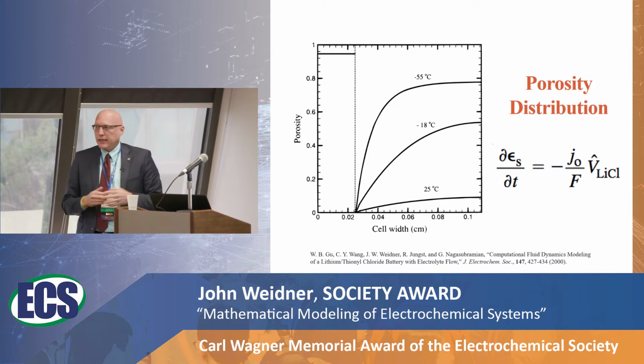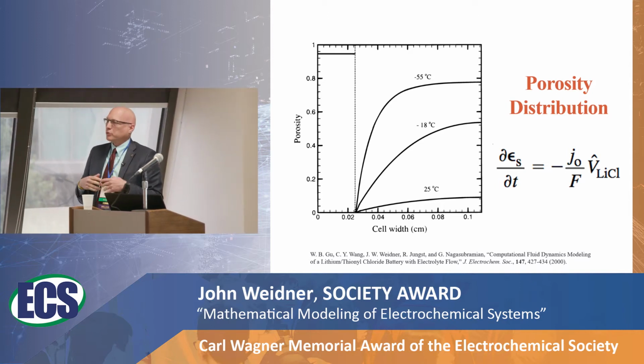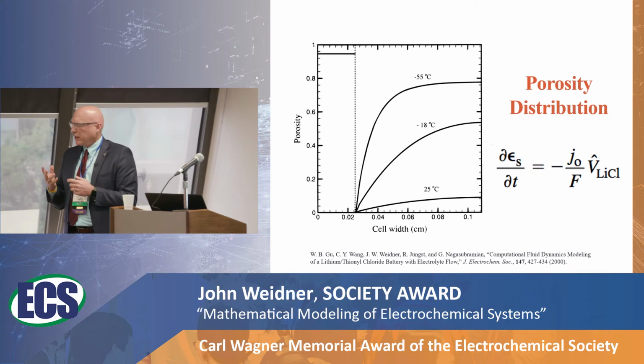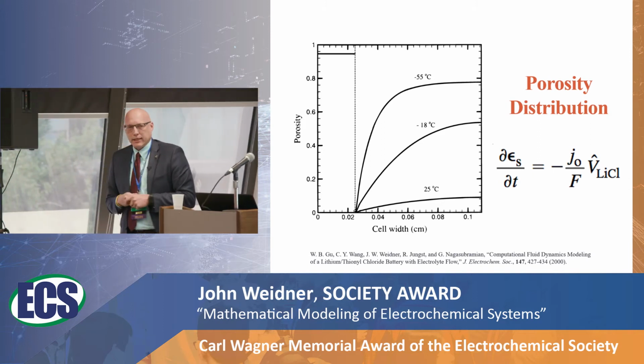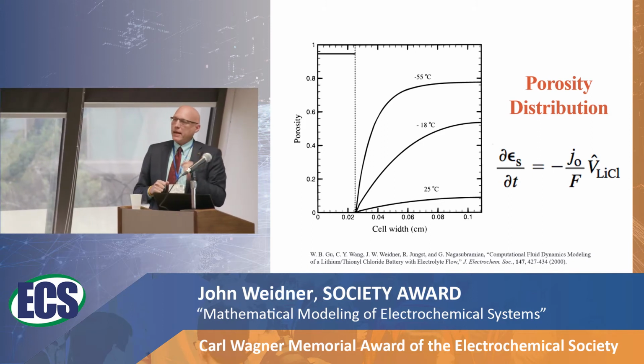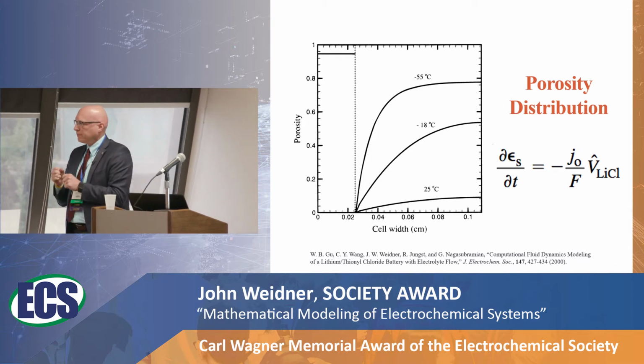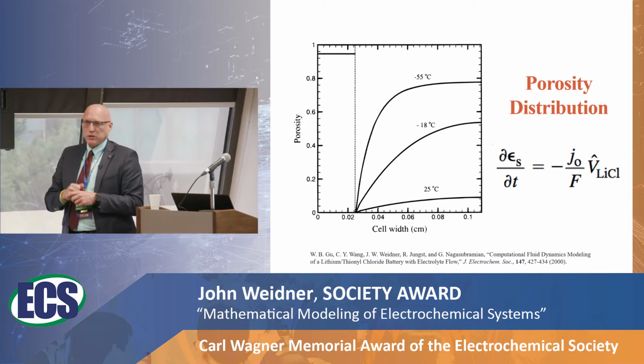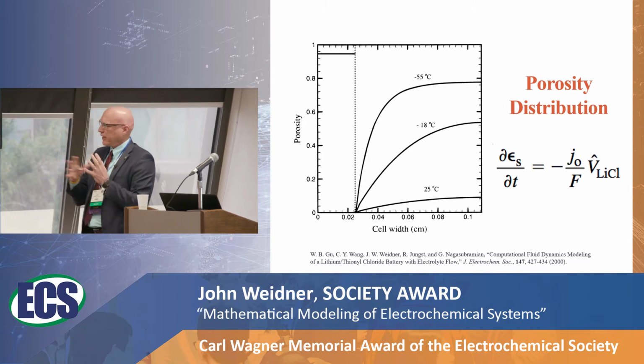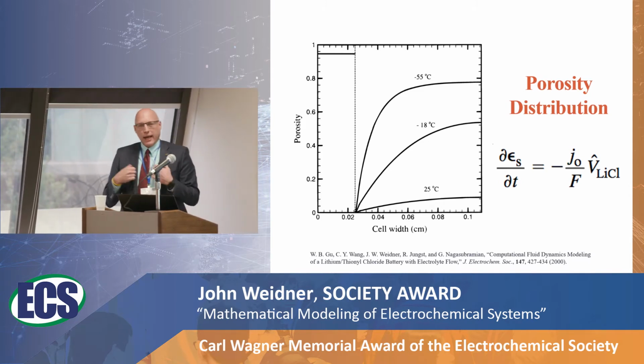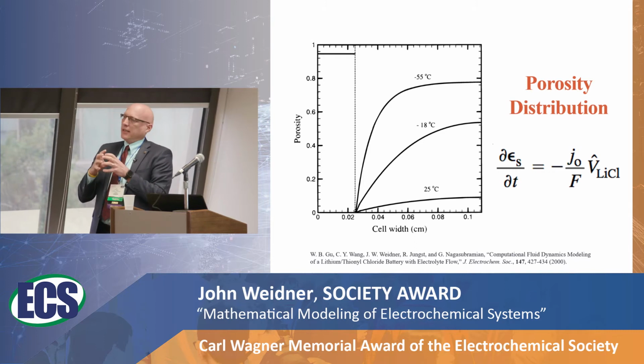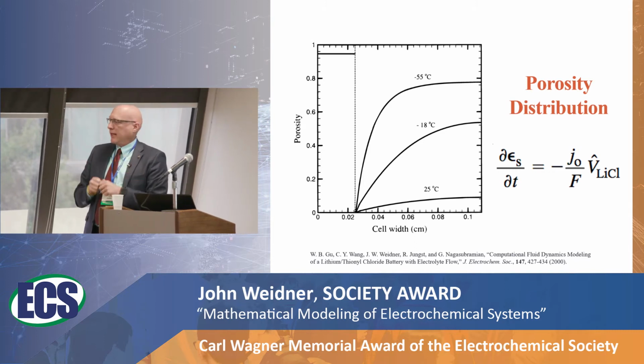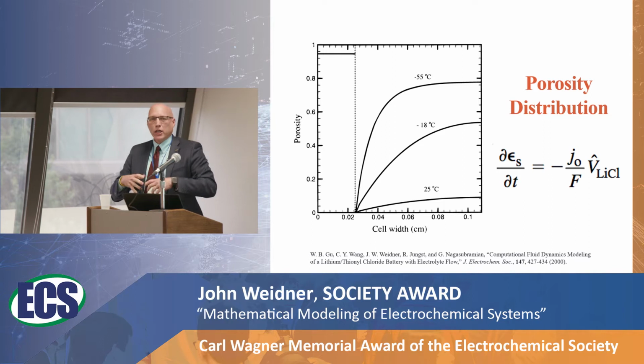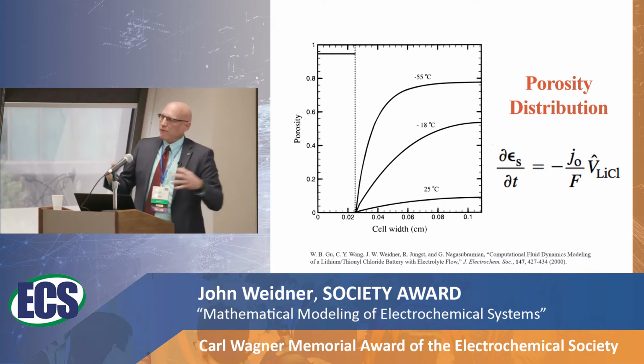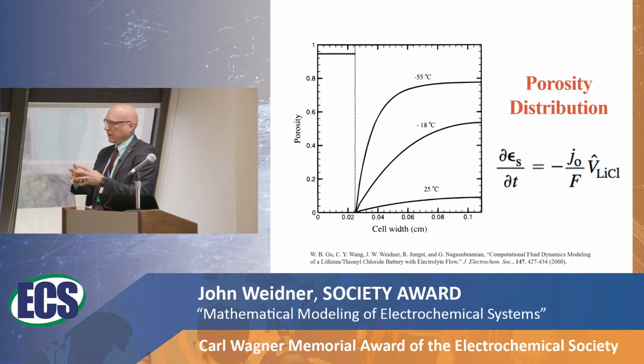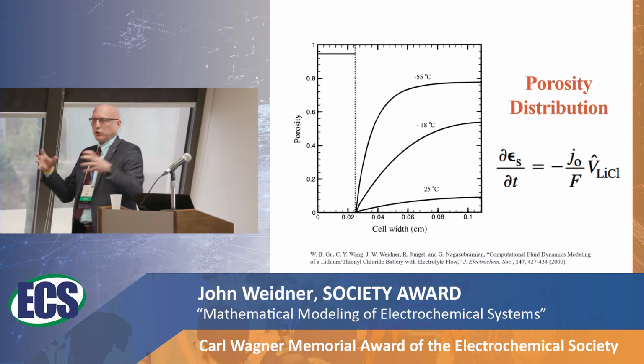One of the things that had troubled us for a while is, we think we had a lot of the physics right, but the troubling thing was that when they made these cells at Sandia, they would roll them up. It was a spiral wound cell, and they'd put it in a can, and they'd fill it with electrolyte, and it was fairly loose in the can. And then when they were finished with the discharge, the can was bulging, and you couldn't get the active material out of there anymore. So clearly there was volume change going on. In other words, the porous electrodes were expanding.